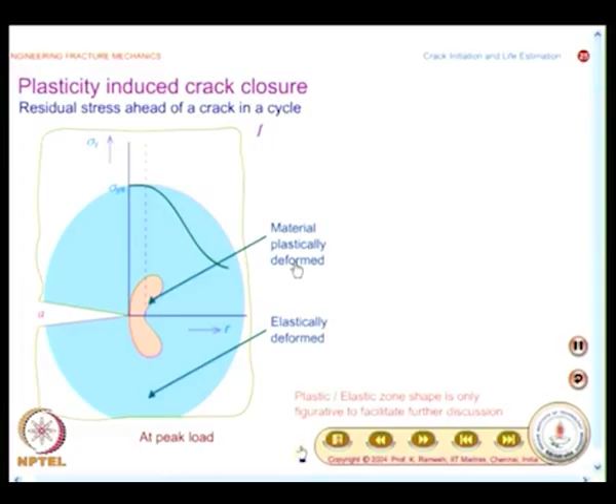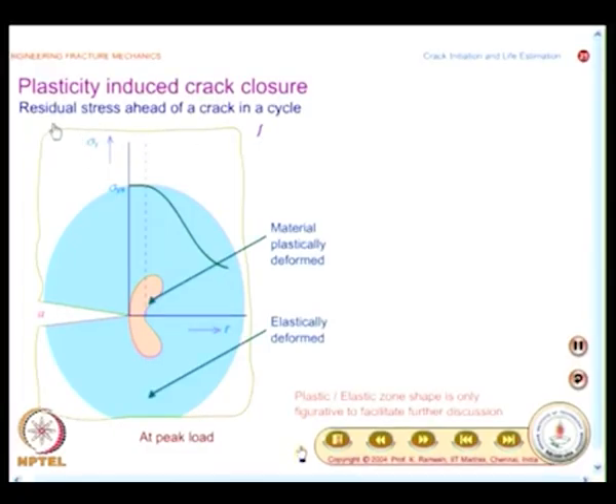So, what you have to recognize is, even though your external loading is much smaller, because of the presence of a crack, when the load is increased gradually from 0 to peak, invariably you will have plastic deformation near the crack tip. So, this happens during loading, and our focus is, we want to see what is the residual stress ahead of a crack in a cycle. This also you have to note, we are just looking at a virgin material, we have loaded it for the first time and you have a plastic zone surrounded by an elastic region, and when I reduce the load, what would happen? Unloading takes place.